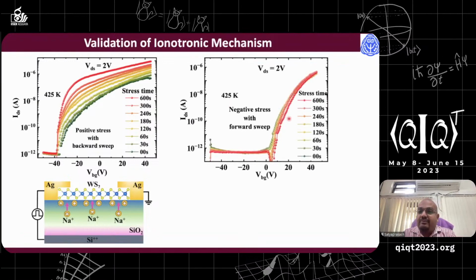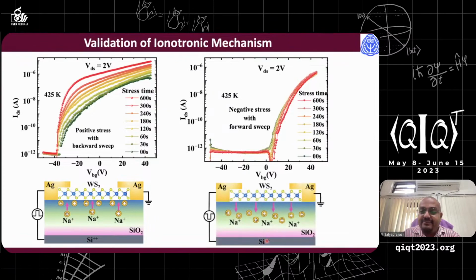Similarly, an interesting result is observed when you apply the negative stress. You apply the negative stress at -40 volt, wait for a similar time, and you see there is no change in the curve, whereas you get this large change here. This is basically because when you apply a negative stress, sodium ions are pumped out from the interface and have no contribution to the conduction channel.